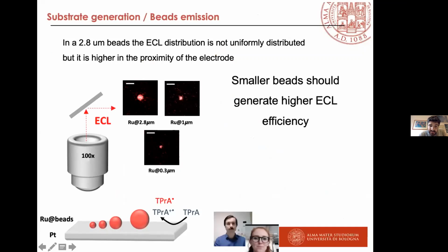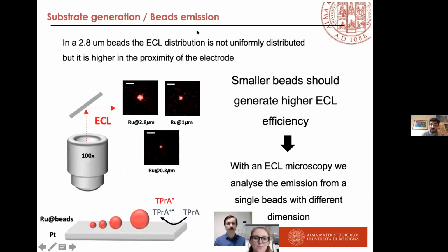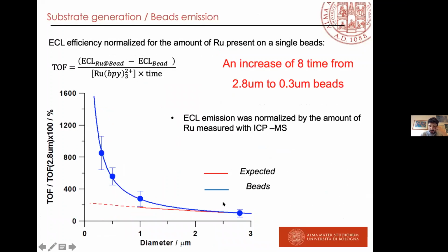We studied different bead dimensions, 2.8, 1 micrometer. We studied many different bead dimensions, and we measured from the top view, with our microscope in the top view configuration. We call this substrate generation because we are oxidizing TPA at the electrode, in bead emission mode. And if we go to quantify the emission, here I don't have time to go into detail of this, but if you go to the